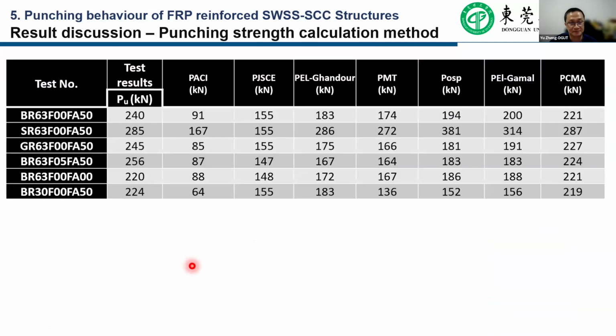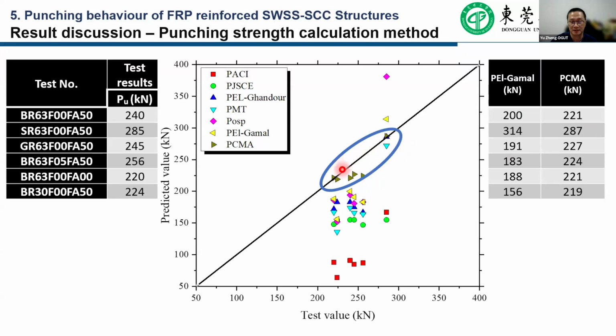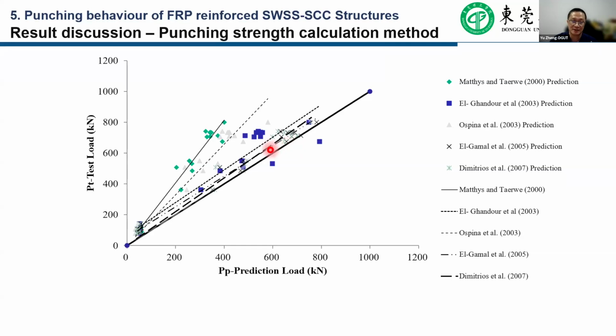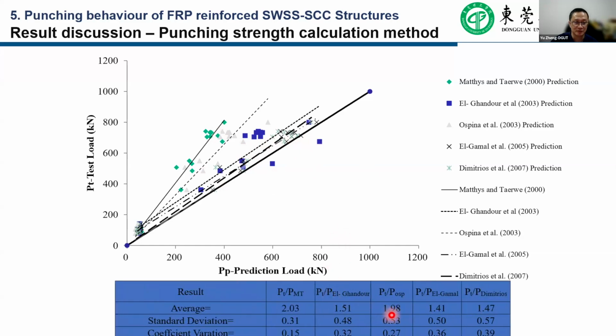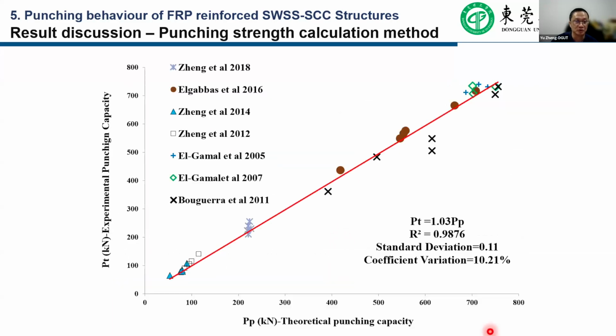After that, we compare our test results with some current design standards and some punching prediction models from published papers. This is our model. We find that our model shows better agreement with the test results. After that, we extend this research to establish a database from the reported literature. We find that the accuracy of the current prediction methods is not good, and the reliability is not good either. But if we use our method on this database, our model can predict the punching capacity for FRP reinforced bridge deck slabs accurately.